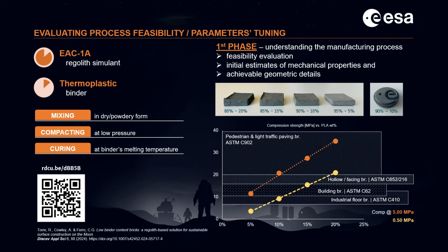We start from the regolith and binder in dry, powdery form. We mix them together. We compact the powders into a mold that will give the part the shape that we want to achieve. And then we cure the part at the polymer's melting temperature. Some of the results you see here have just been published in Discover Applied Sciences, so I really recommend you have a look at the paper.